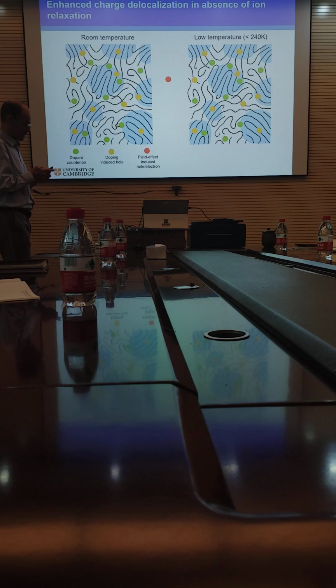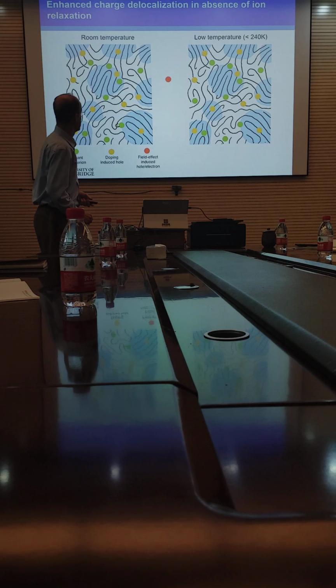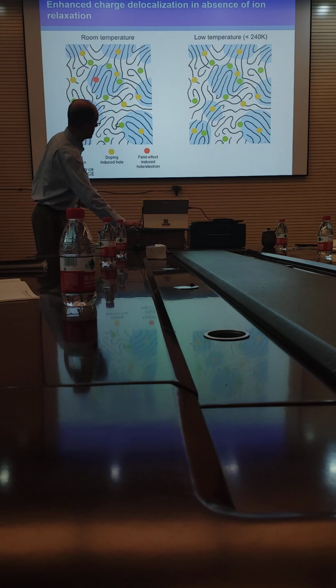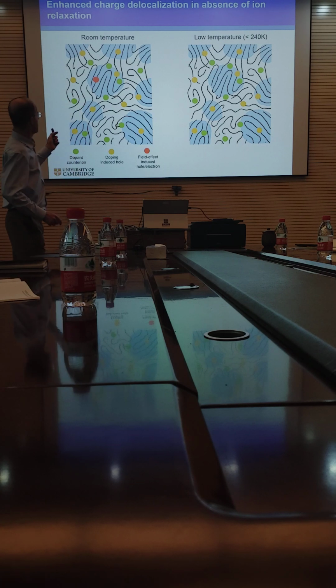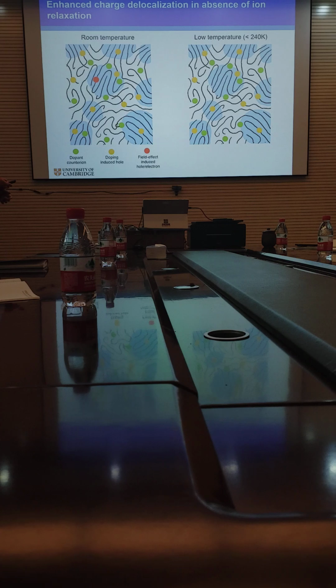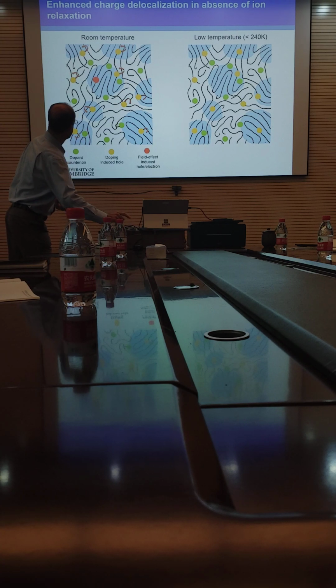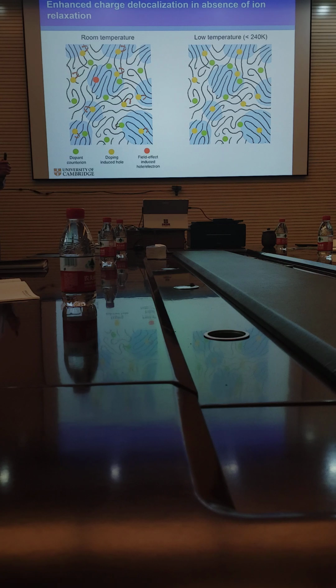And so when we do this, that extra electron goes in, or extra hole goes in. And then what's going to happen? At room temperature, the first thing that's going to happen is that the other electrons will feel the presence of that extra hole and they will respond. They're probably moving away because there's a repulsive interaction with the other electrons.